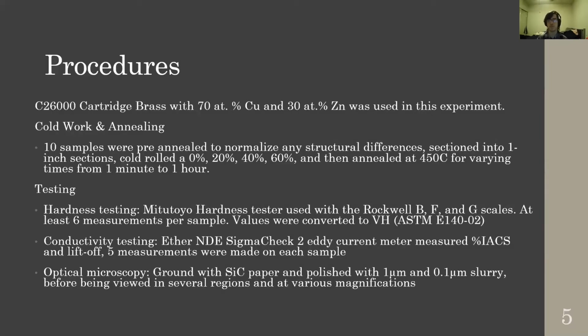So the procedures on how we carried this out: like Ryan said, we have 70% copper, 30% zinc cartridge brass that we used. All of our 10 samples were pre-annealed to normalize the microstructure to the same state. And then they were cut into different sections and cold rolled at 0, 20, 40, and 60% reduction in the thickness of the strip. And all of them were annealed at 450 degrees C for varying times, for as little as 1 minute and for as long as 1 hour. For the testing of this microstructure, we performed hardness testing on a Mitutoyo hardness tester on the Rockwell B, F, and G scales, depending on the softness or hardness of the material.